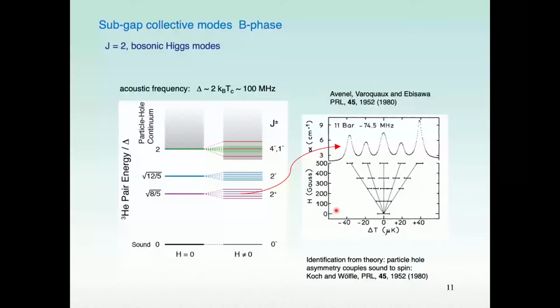And simultaneously with that, I think within months, the theoretical explanation for the observation of this square root of 8/5 state was made by Koch and Wölfle, because it's part of the real part of the order parameter of superfluid helium-3B, and it couples only to spin. It wasn't thought, first of all, that might be the explanation. However, it was shown by Koch and Wölfle that indeed that's the explanation.